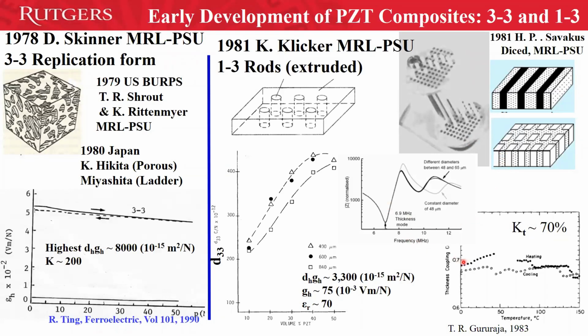Gururaja made a huge investment on characterizing high frequency applications of these composites. This is an example of thickness coupling coefficient versus temperature. It is so stable, with a very good thickness coupling coefficient of about maybe 70% or so, all the way up to 150 degrees C.